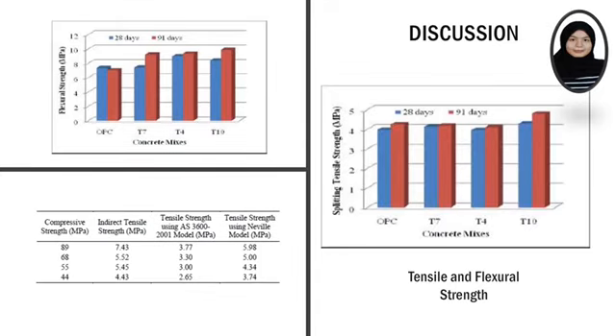Olivia and Nikraz reported that both splitting tensile and flexural strength of the geopolymer concrete increased with increasing concrete age. The splitting tensile strength values of fly ash-based geopolymer concrete were comparable or higher than those of OPC-based control concrete. The tensile strength of optimal mix T10 was 8 to 12% higher than that of OPC concrete at 28 and 91 days. This could be due to the effective bonding between the geopolymer matrix and aggregate. The flexural strength of the geopolymer concrete was found to be 1 to 1.5 times higher than that of the OPC concrete at 28 and 91 days.